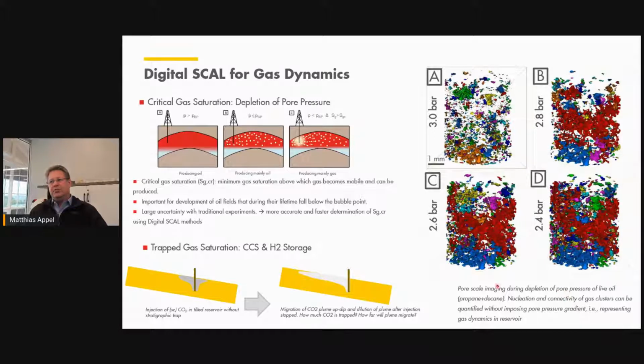Digitally, with multiscale imaging, you can basically make these experiments as shown here on the right. You take a two-phase fluid, you are depleting the pore pressure of the two-phase fluid. And what we are looking at here are individual gas clusters only, not the liquid. And different colors indicate different connected gas clusters. You see at relatively high pressure, only very small clusters, a lot of different colors, very disconnected. So we are not in the situation that the gas clusters are connected. But while we are depleting the pore pressure of that rock, you see that eventually a massive red cluster develops, connected from the bottom to the top, therefore establishing the critical gas saturation in that case.